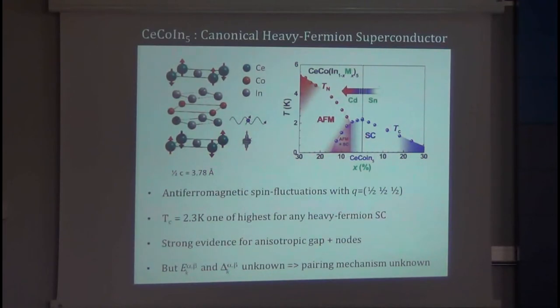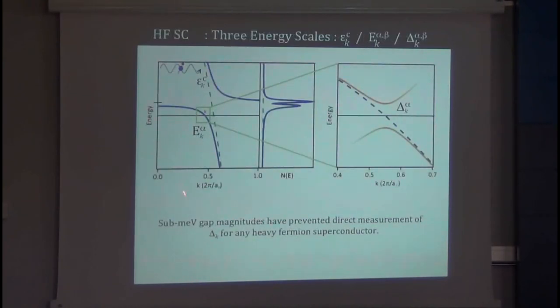They were both unknown. I forgot to say, although the density of states as a function of energy, showing you what a heavy fermion superconductor looks like, was measured quite a long time ago. In fact, pioneering experiments done right here at UAM. The actual momentum space structure of the superconducting energy gap of a heavy fermion superconductor had never been measured for any heavy fermion superconductor. So here's what you got to do.